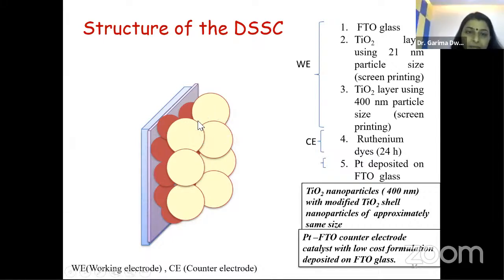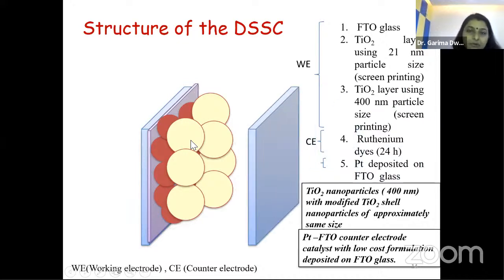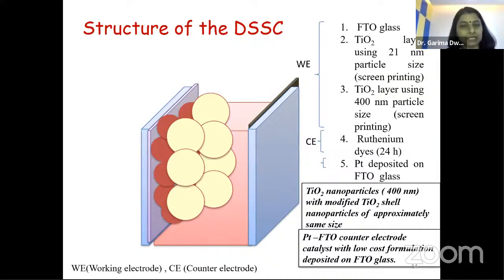And these particles are a little bit bigger in size, so very little dye is adsorbed on this particle. In case you can see on the glass slide also. This is a counter electrode. We deposit a layer of platinum on this FTO glass, and at the end we just insert the electrolyte and seal this cell. So this is like a sandwich type assembly.